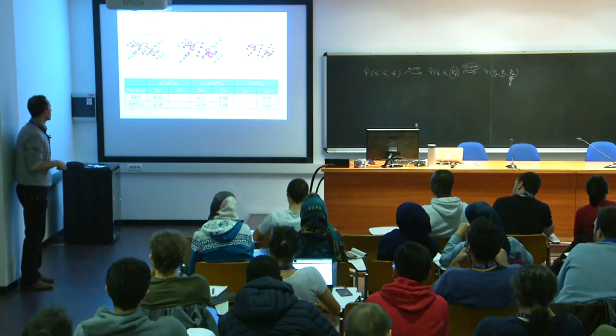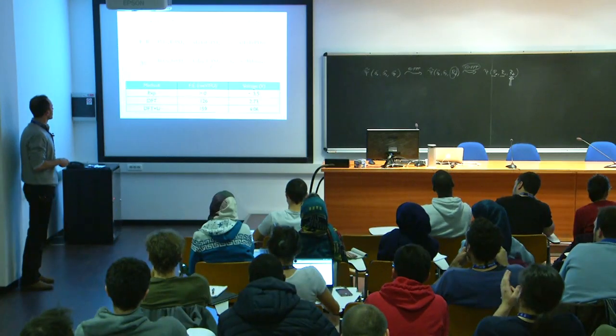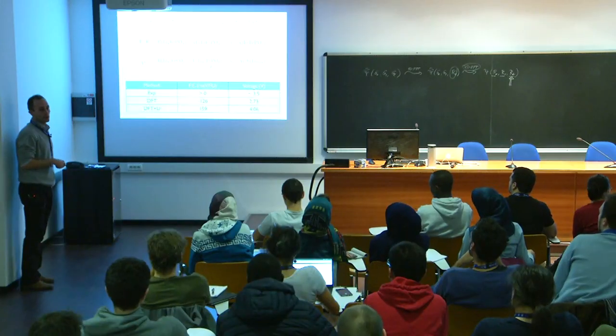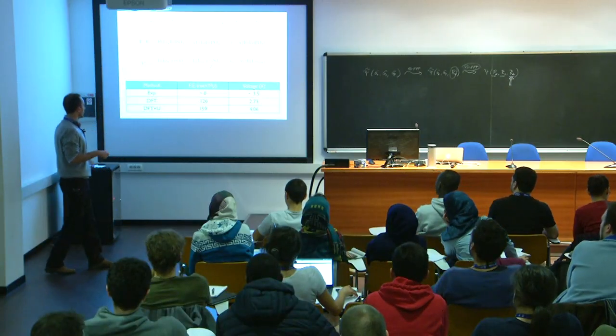We will see also this in the exercise this afternoon. So we will have a chance to directly see from the output. And also energetics changes a lot in the right direction. So you get positive formation energy for the intermediate lithium compound, and also voltages that are much closer to the experimental value of 3.5.